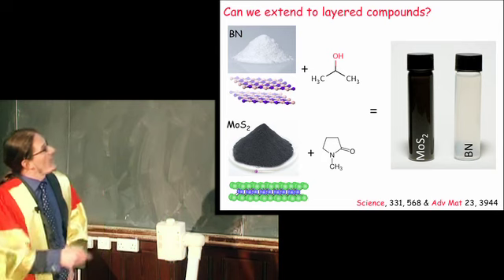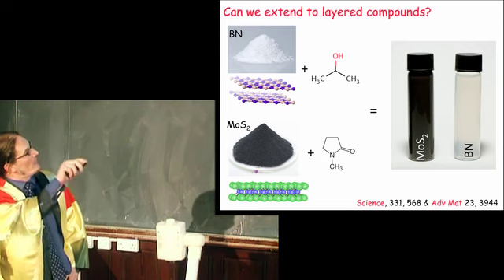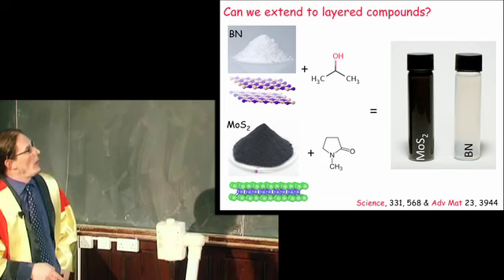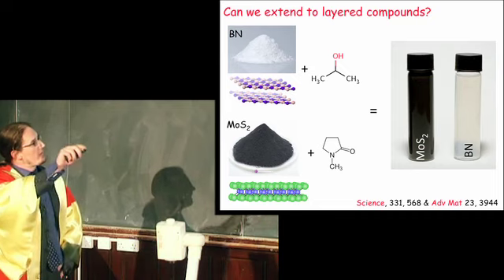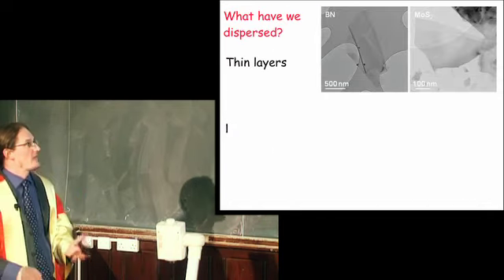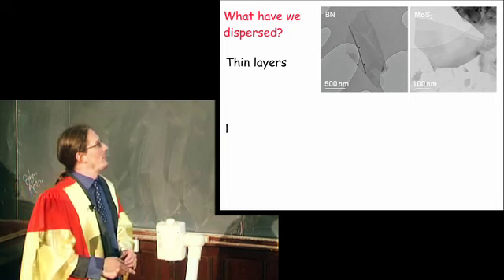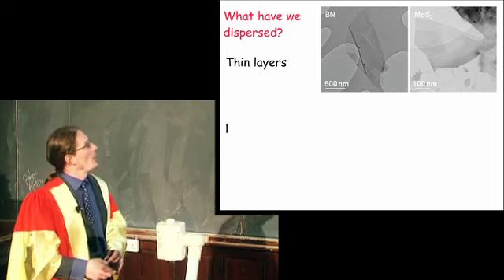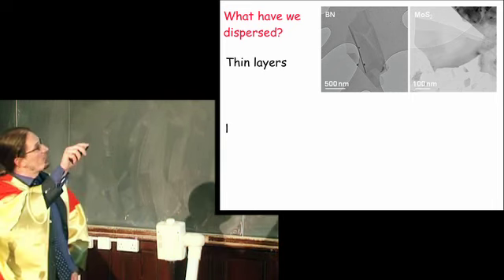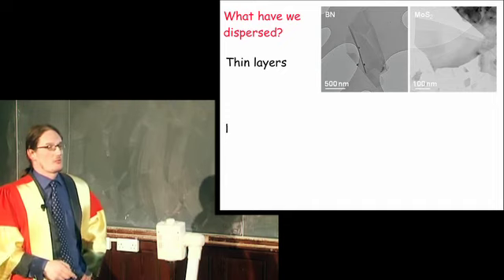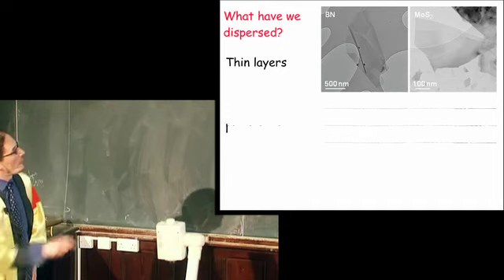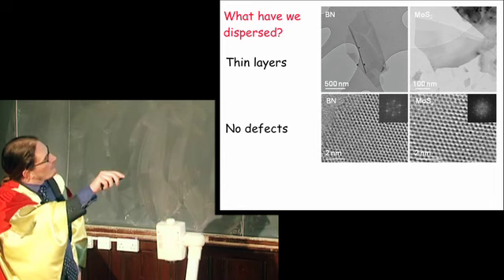We sonicated, and we get, in the case of molybdenum disulfide, a black liquid, in the case of boron nitride, a white liquid. The question is, do these liquids contain exfoliated individual layers of the layered compound? Well, if you look in with a microscope, you do indeed see these two-dimensional structures. And if you look in closer, you'll see this is at atomic resolution.